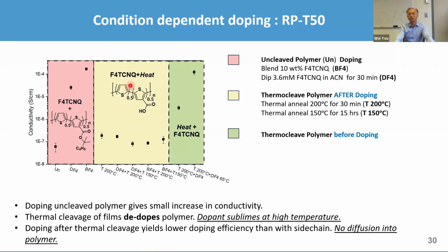If you take F4TCNQ together and heat them all up, you actually end up with almost no doping effect. This is because under high temperature, as you are using high temperature to remove the cleavable side chain, F4TCNQ also sublimes. So you end up with no doping effect.